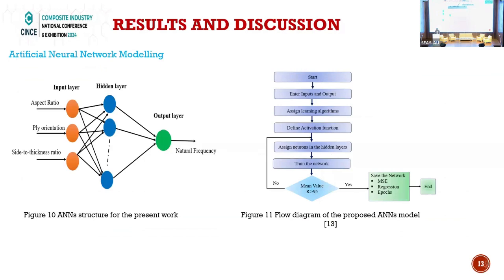For that, I have taken 3 inputs: aspect ratio, ply orientation, and side to thickness ratio, and my output is the first 2 modes of natural frequency. The aspect ratio I have taken from 1 to 5 in intervals of 1, and the ply orientation is 0 degree, 15 degree, 30 degree, 45 degree, and 60 degree. And the side to thickness ratio is taken as 20, 40, 80, 160, and 320.